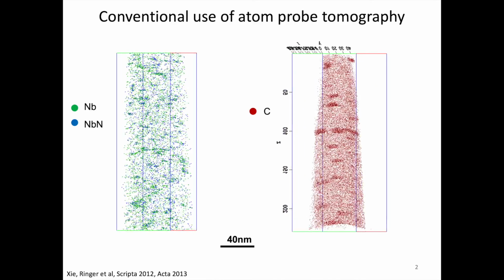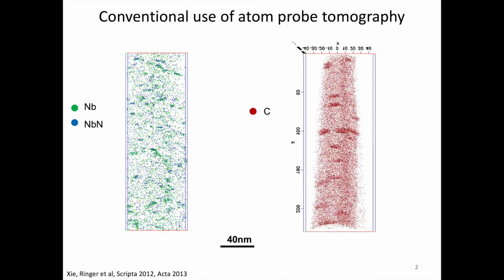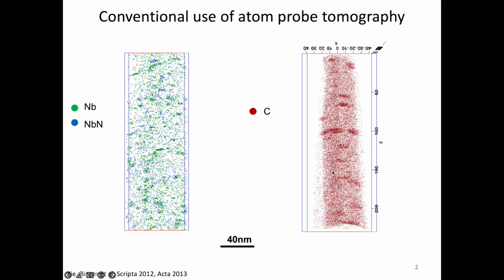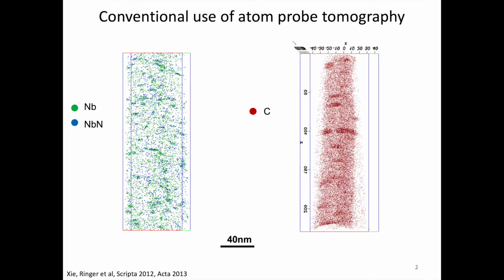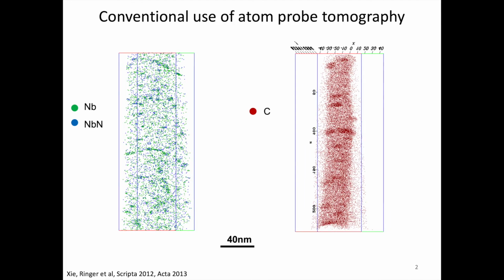This is because the dislocations in the material act as a preferential nucleation site for heterogeneous nucleation. In the example on the right, you see a lot of carbides at the grain boundary, but not outside the grain boundary. In this case, the grain boundary is acting as the heterogeneous nucleation site for those carbides formation.